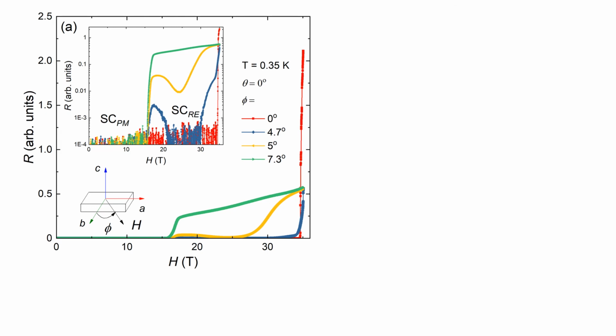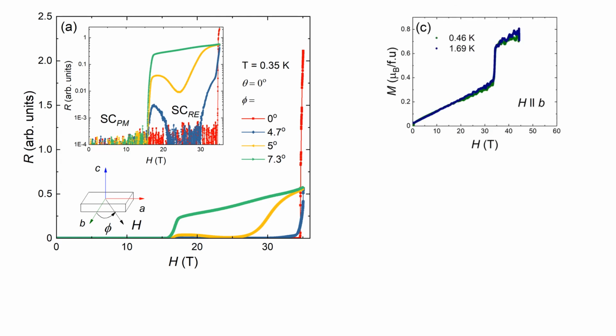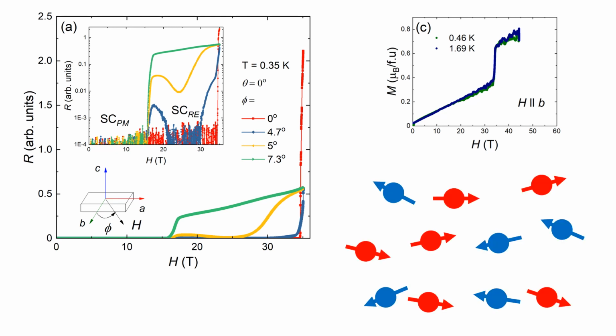Okay, I showed you there's a sudden increase in resistance at 35 Tesla when the magnetic field is along the b-axis. It goes to a normal state. But what kind of normal state? To answer this question, we measure the magnetization. There's a large increase in the magnetization value, indicating a change in spin orientation. Likely, this is what happens.